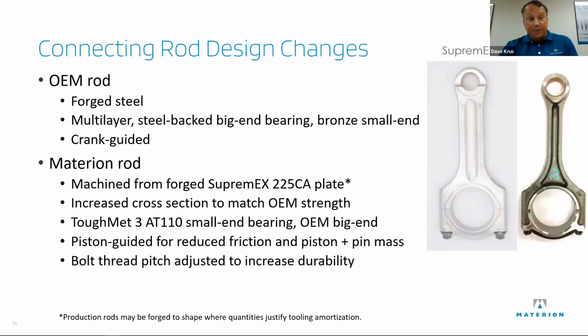The big change was the connecting rod. The OE rod was forged steel. It had your traditional multi-layer big end bearing and a bronze small end bearing. And it was crank guided. So we made the Materion one, the Supreme X one, out of plate. The reason for plate is we weren't making enough to justify forge tooling. You could forge it to near net size, but for availability, just at the time, we cut it out of plate.